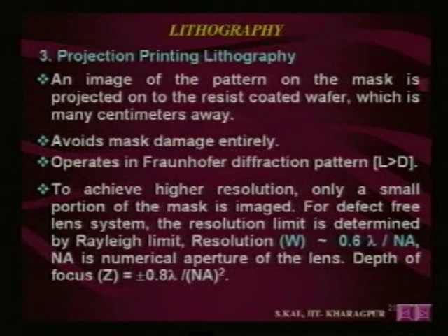For a defect-free lens system, the resolution limit is determined by the Rayleigh limit, and here resolution is given by 0.6 lambda divided by NA, and NA is the numerical aperture of the lens system. Depth of focus is given by plus minus 0.8 lambda divided by NA square.